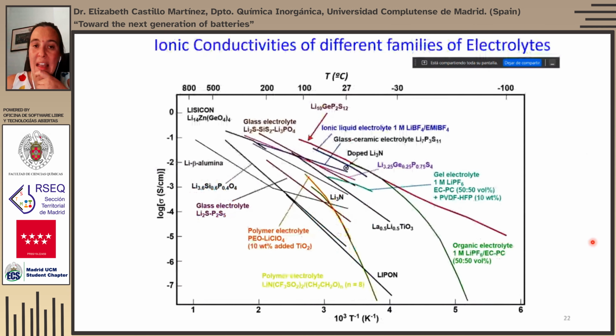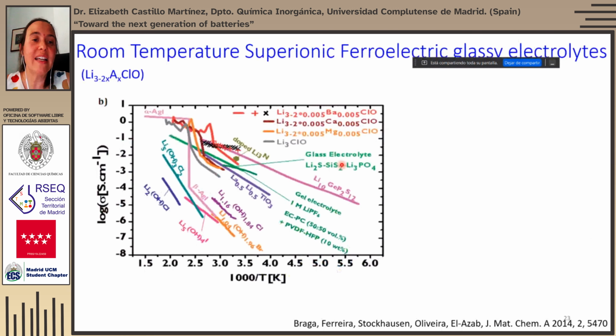If we look at a plot of ionic conductivity, this is the logarithm of the ionic conductivity versus the inverse of temperature, we can see that the liquid organic electrolyte has conductivities at room temperature in the order of 10 to the minus 2 Siemens per centimeter. And some of the sulfides that have been proposed have similar conductivities as well. However, what is more striking, and this is quite recent, is that there are some lithium-rich or sodium-rich glass electrolytes, derived from the antiperovskite structure, that show conductivities very comparable to those of the liquid electrolyte, and even higher than that of the sulfides.